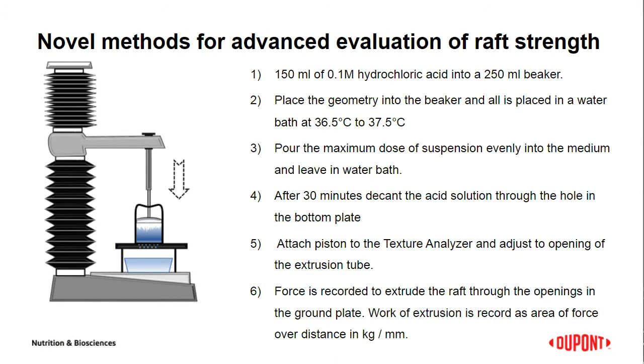Many thanks. The second method we have used to characterize the performance of the raft was first described by Detmer et al. in 2005. This method has now been further modified by us. The method itself is based on a forward extrusion process and is illustrated on this graph. The geometry is first placed into a hydrochloric acid solution, in which the anti-reflux formulation is poured afterwards. The beaker containing all of these is then stored for 30 minutes at 37 degrees C, and afterwards the hydrochloric acid is decanted through the holes in the bottom plate.